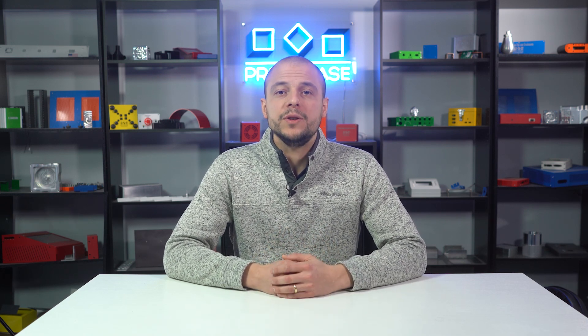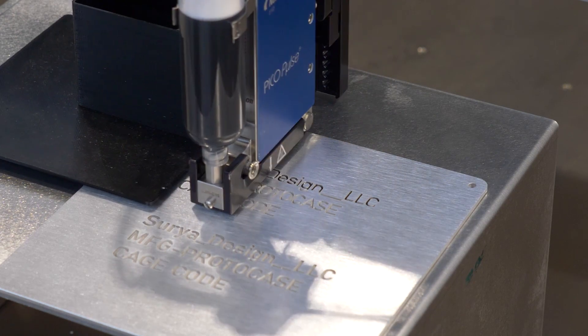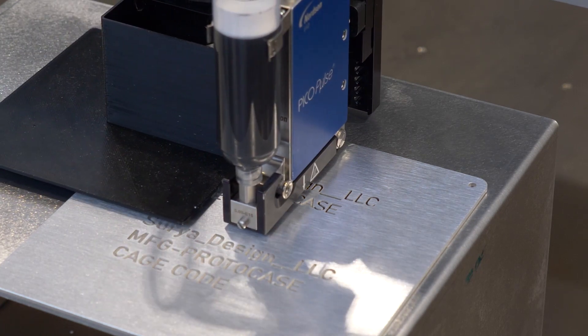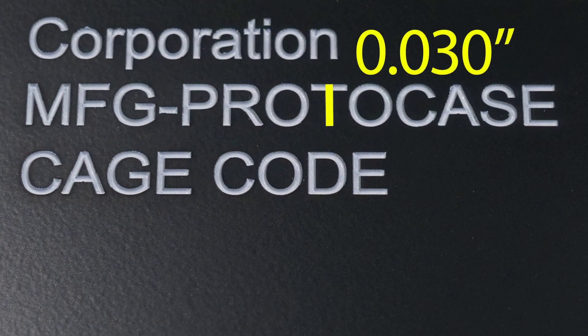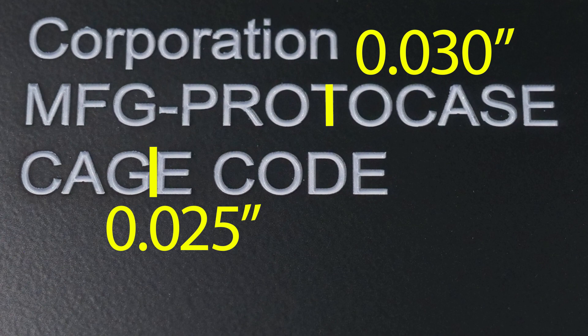The line thickness of the font you select is very important and it will depend on the style and height of the font you select. This value must be at least 30 thou or three quarters of a millimeter in order to be compatible with our ink fill process. Epoxy ink is a high viscosity fluid which affects its flow and layer thickness properties. The smallest drop of fluid we can achieve must be shot by the dispensing valve at high enough pressure and temperature to be able to flow, while falling into the engraved channel without touching the edges of the marking or spraying the top of the surface. Our epoxy inks are extremely durable, therefore once they touch a part, these cannot be wiped up completely. Keeping this channel width at or above 30 thou ensures no overflow or smeared edges and keeps your part marking sharp and legible. We also recommend keeping spacing between characters at or above 25 thou for best legibility.